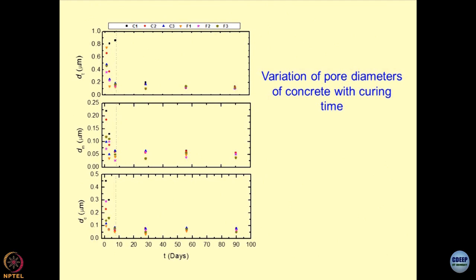This is a good example of how DT varies over a period of time in the case of concrete which is getting cured. Why I am citing this example is that concrete is still a very stable material as compared to soils. But when I deal with minerals which are active, or processes which are very active as a function of time inside the soil matrix, it becomes very difficult to capture the phenomena by using MIP. In this case, you see that DT, DM and DC decrease as a function of time, and this is how we define the curing of the concrete.